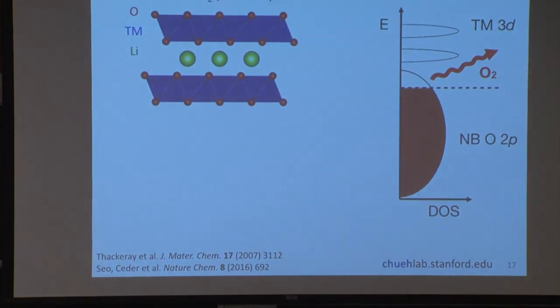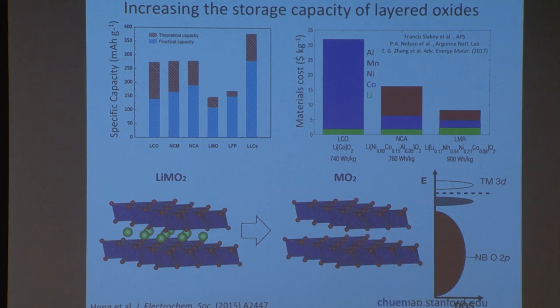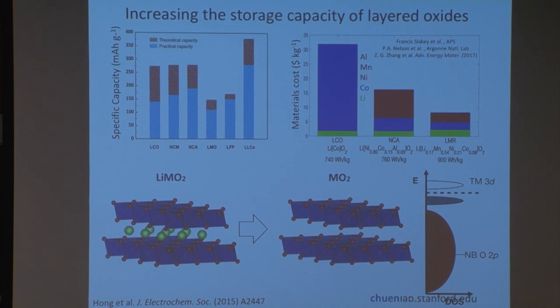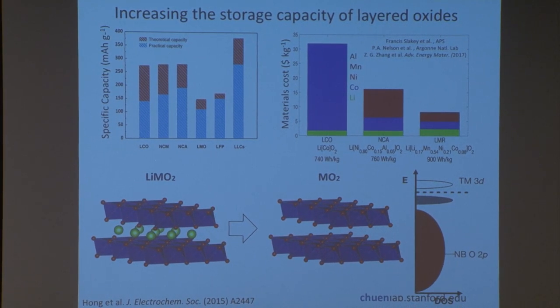So you can imagine when you go from an empty layer to a full layer, here. So as you go from this to this, there's already, you know, several percent change in the lattice constant, even if the material doesn't rearrange itself. So that you have to live with, because we want to get the lithium in and out of the system. So I would say it's an effect, but it's probably a small delta on top of a large expansion already. But this is something that we have to address in the material. So the graphite carbon electrode in your phone expands by almost 10%, but you can do this several thousand times over.